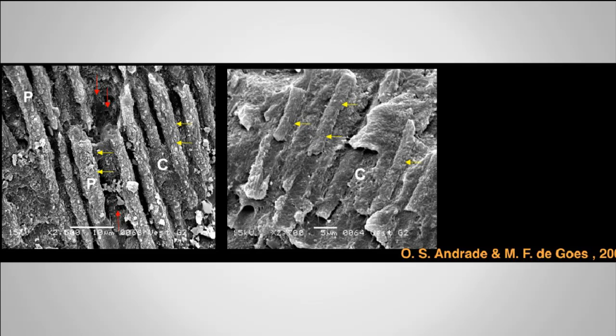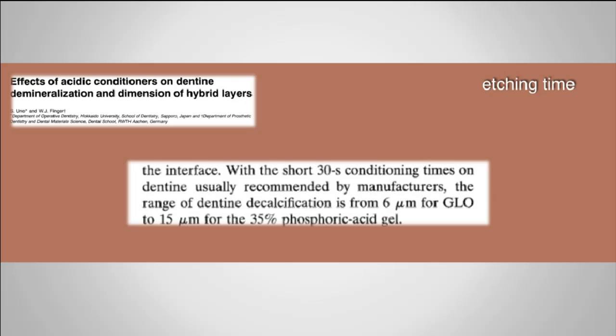If you see this problem in the SEM, basically it is this image. On the left side, you have the dentin. On the right side, you have the composite. This is exactly the interface of the restoration. On the left side, you can see some failures in the penetration of the adhesive. These failures are basically these spaces. You demineralize the dentin, you expose the collagen, but for some reason your adhesive doesn't penetrate these spaces. And when your patient bites on these spaces, he feels a bite sensitivity.